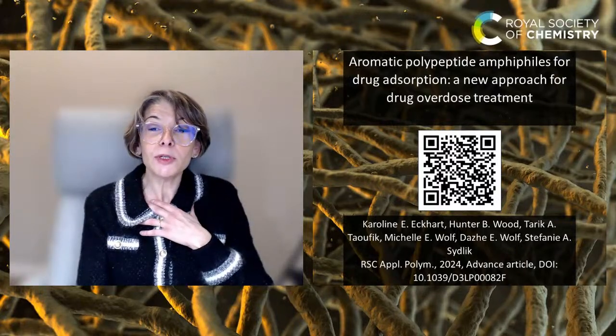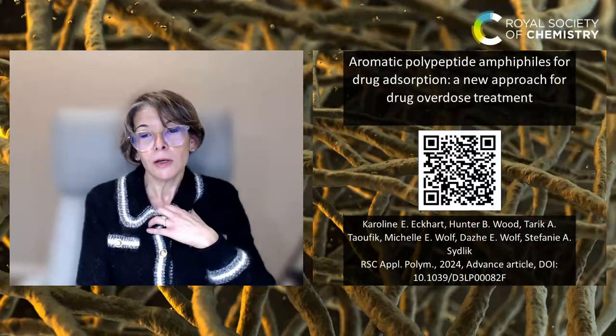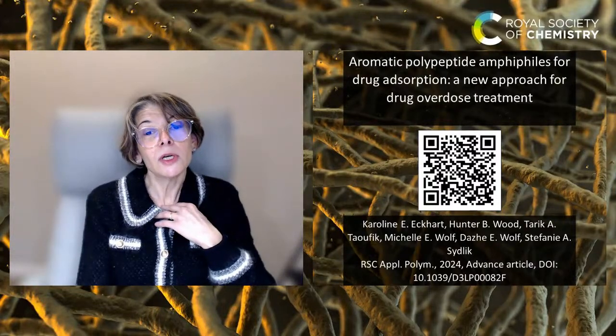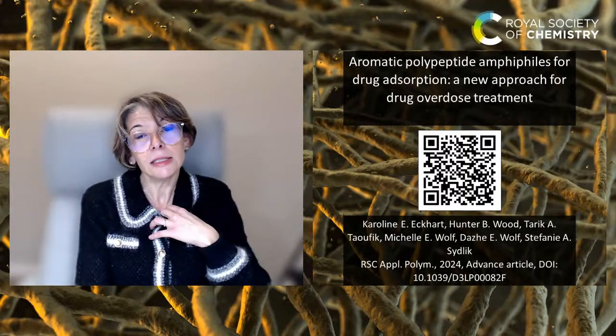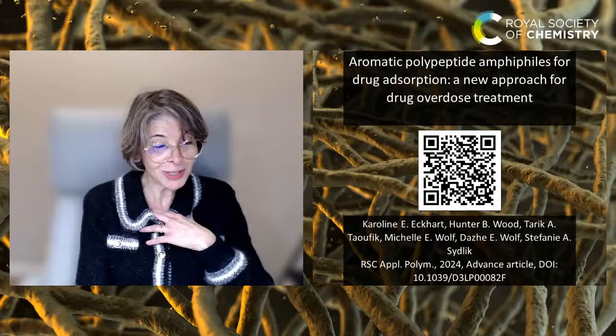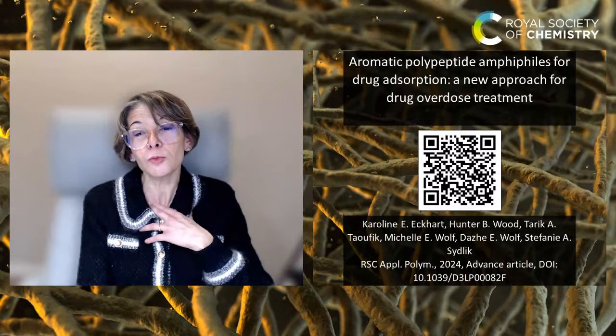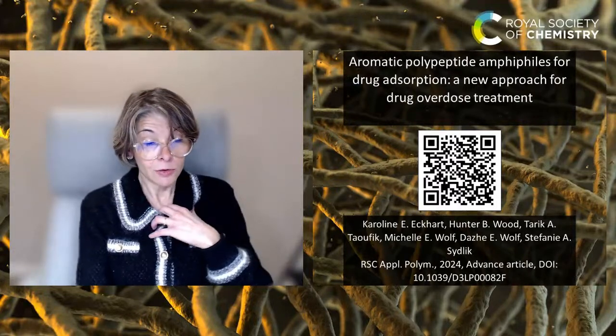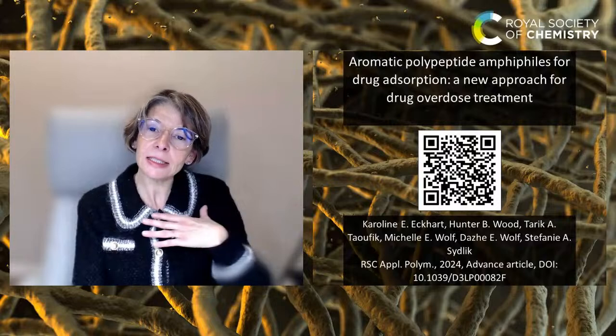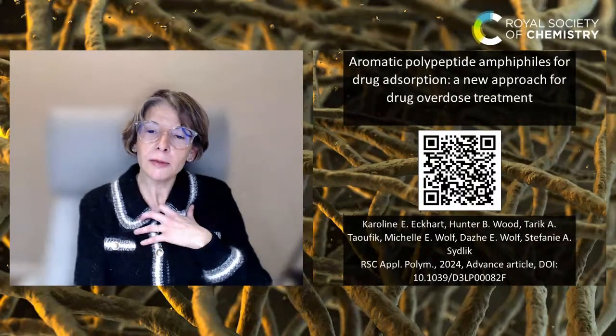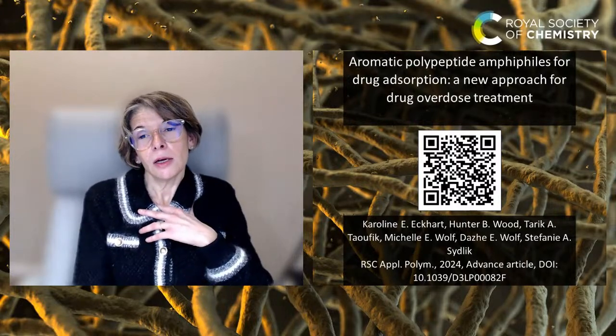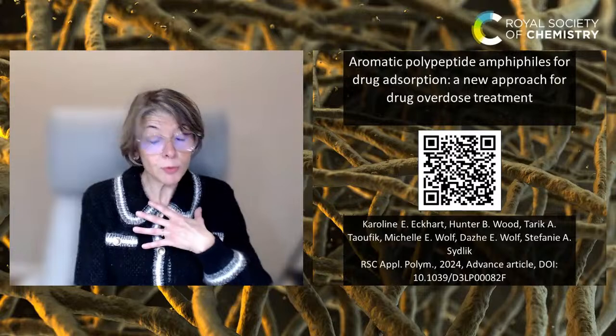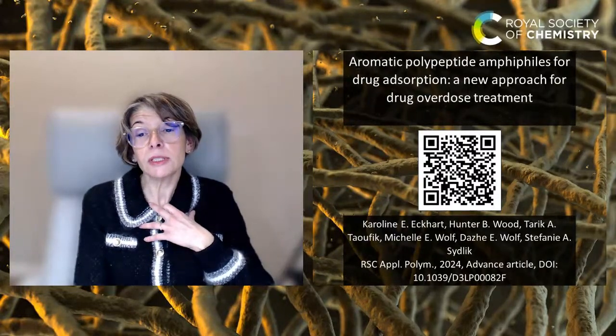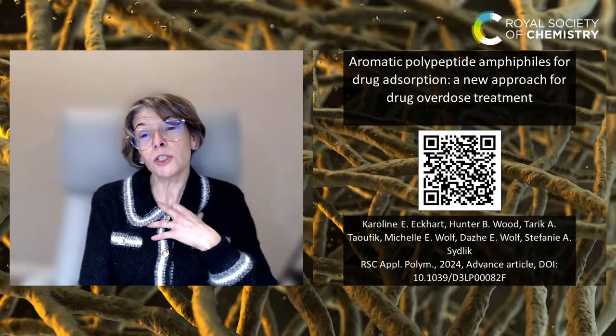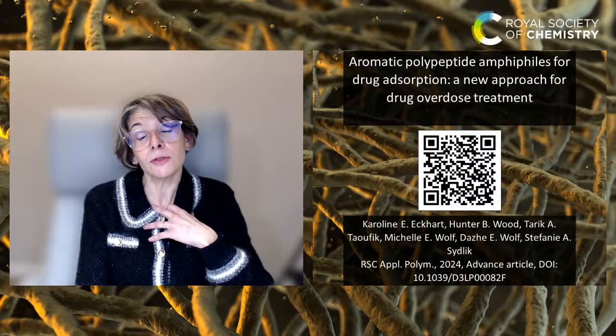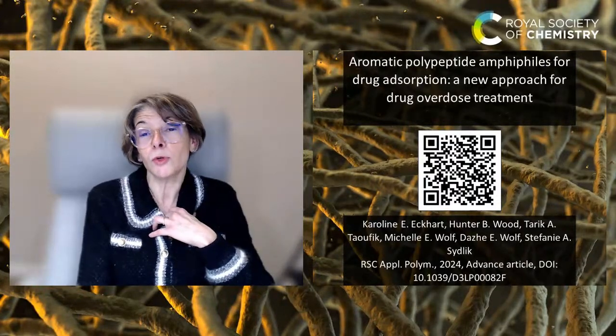And more specifically, they prepared a water-soluble, pH-responsive block containing cationic lysine and anionic glutamic residues to confer solubility and also to promote adsorption of drug through electrostatic interaction. And then they extended this block with hydrophobic aromatic polytyrosine, which promotes the formation of particles which sequester the adsorbed drug and which also facilitate pi-pi stacking interaction with aromatic drug molecules.